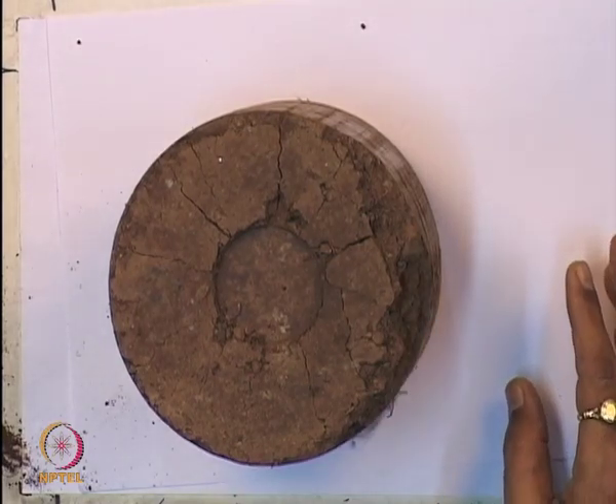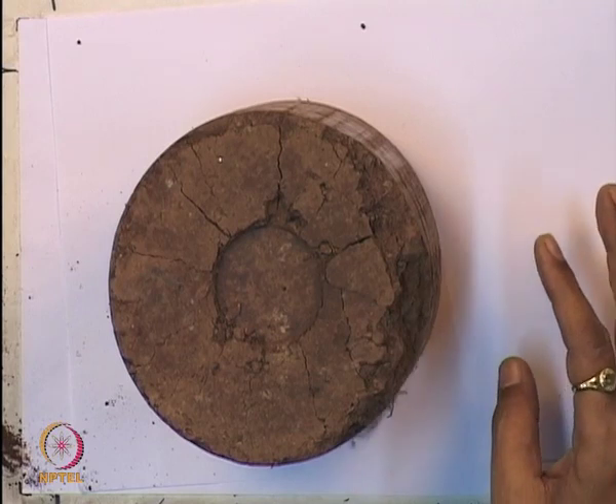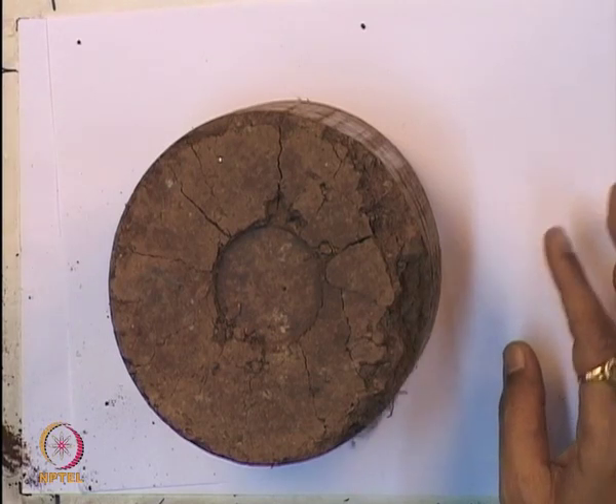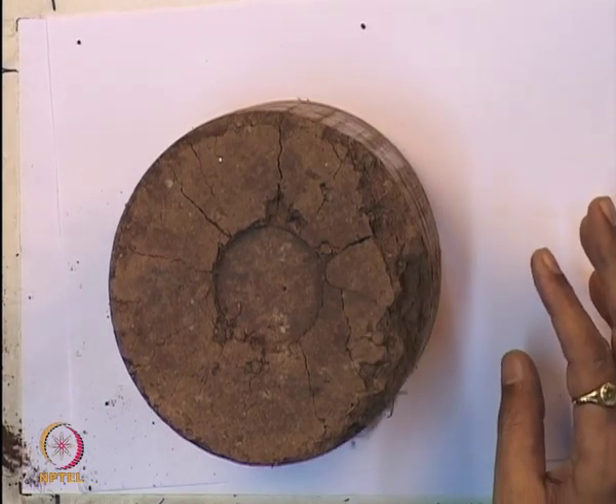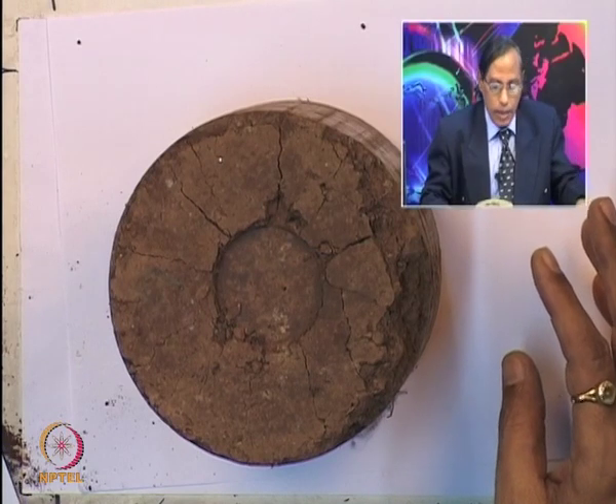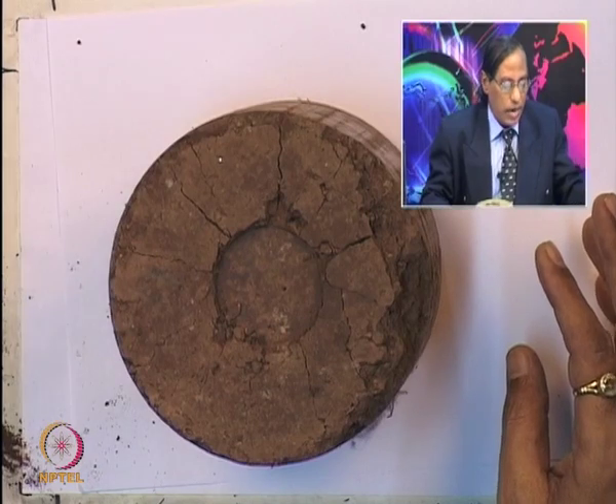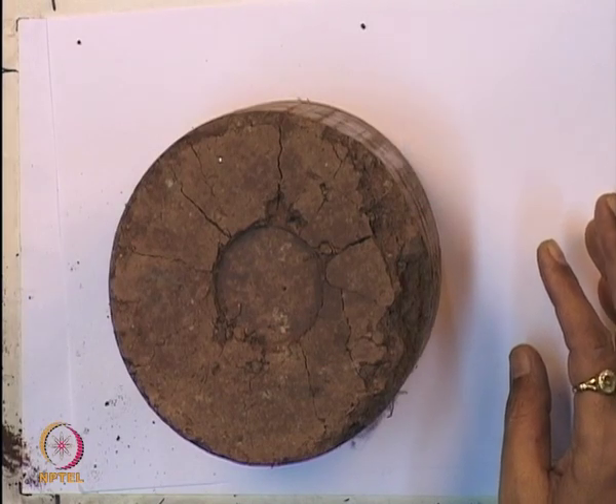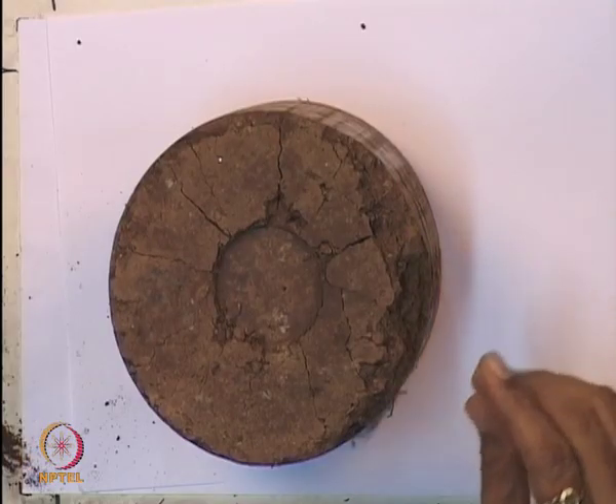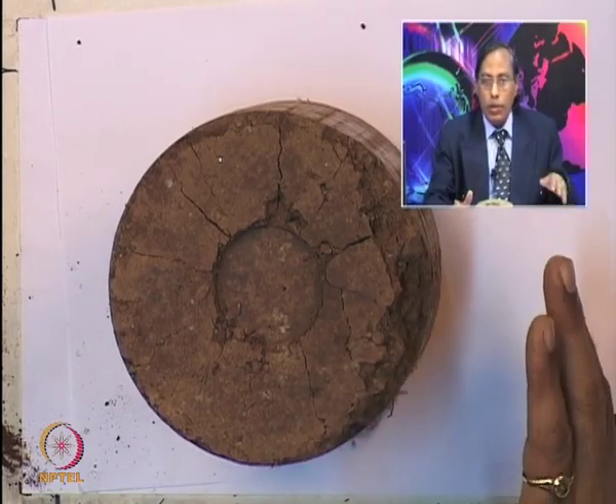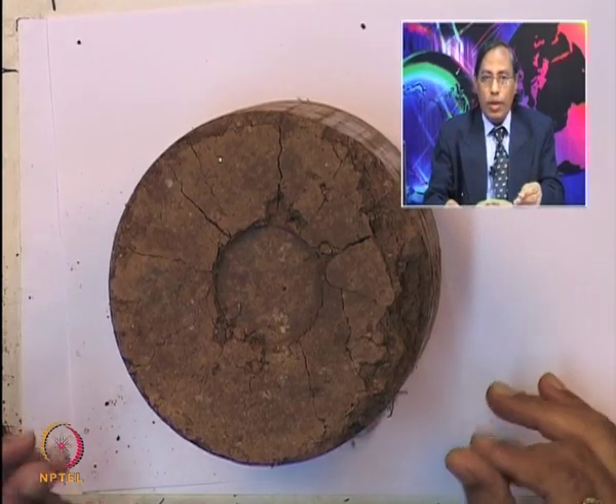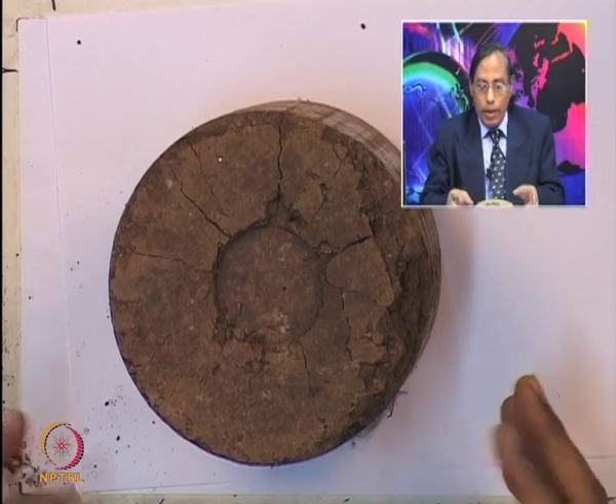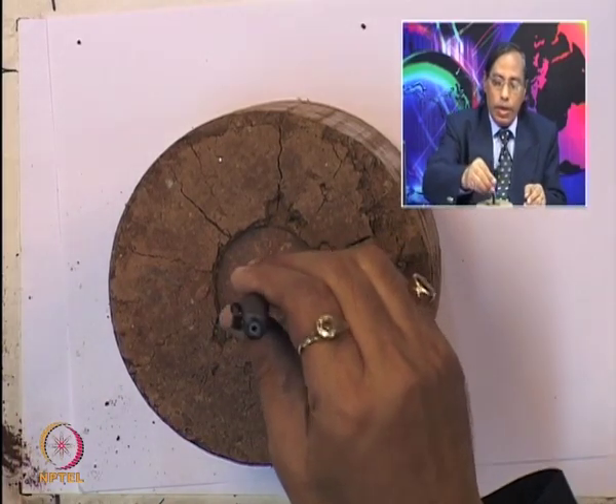You can see here this is the CBR mold, in which we have performed the test. The nano zinc oxide material also has been included, and different types of fly ash and also cement have been used. In case 1, soil with 2% cement and 0.1% nano zinc oxide has been used, and case 2 is soil with 4% cement and 0.2% nano zinc oxide, and case 3 is soil plus 6% cement plus 0.3% nano zinc oxide. So this is one of the samples on which the test has been performed, and you can see it is very hard.